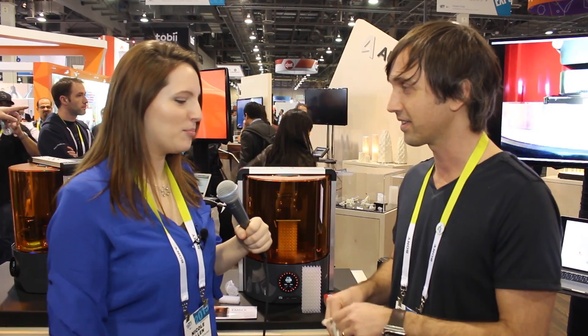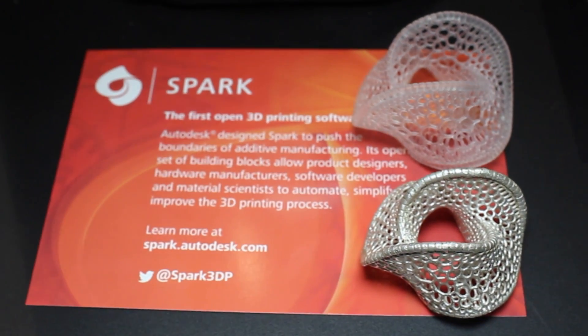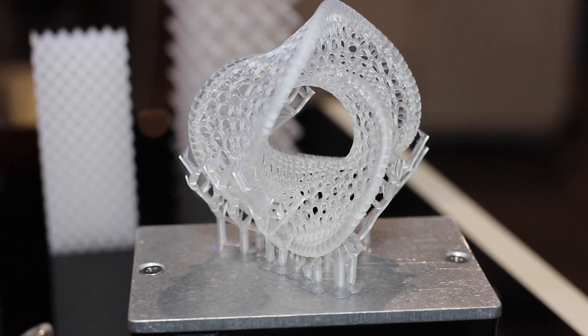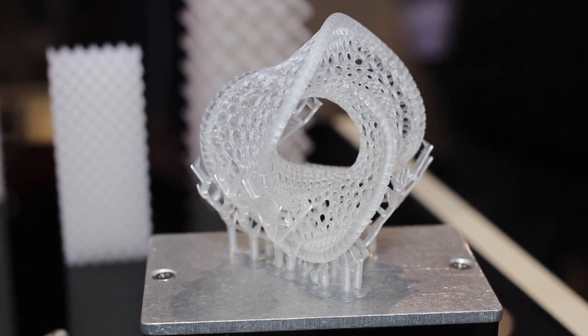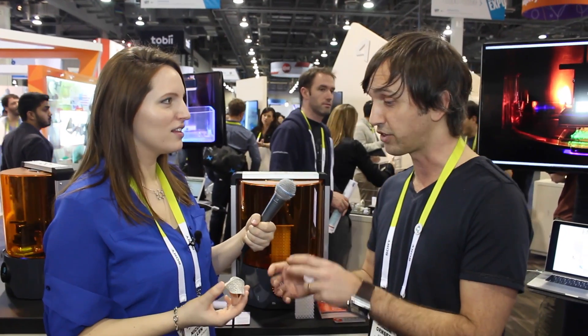This is an example. Just think of all the applications of 3D printing that even a decade ago we had no concept of. And also the design tools. I've got this in my pocket because it's real silver — we didn't polish this or anything, this is just how it came out. This was a 3D printed model. I actually designed this, and we printed a 3D printed master and then applied the investment casting technique — put some investment slurry, then baked it, burned it out to create a cavity, and then filled the cavity with molten silver. That's how we created this object.